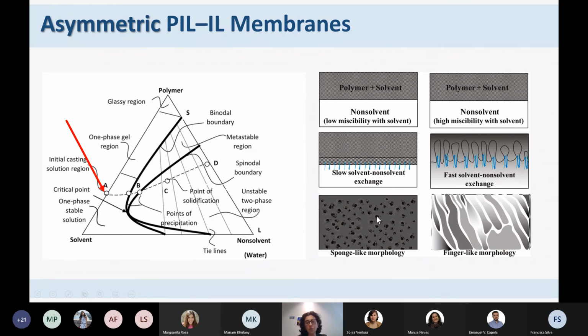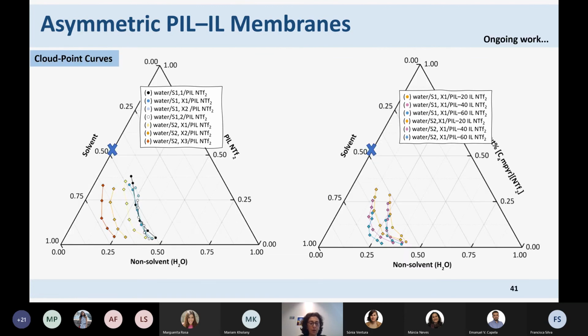Now, the trick is to choose the solvent and the non-solvent. When I have a non-solvent that has a low miscibility in the solvent, we have slow exchanges and we end up in a porous structure that has a sponge-like morphology. When we have a non-solvent that has a high miscibility with the solvent, we have a fast exchange between the solvent and the non-solvent, and we end up with a finger-like structure. So we have to optimize all these parameters. So here are the phase diagrams that we've been carrying out.